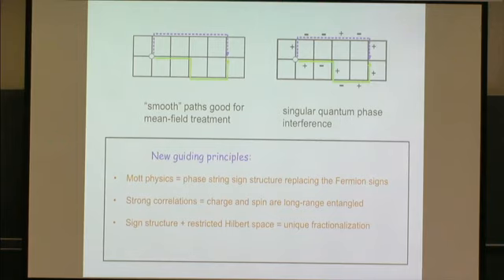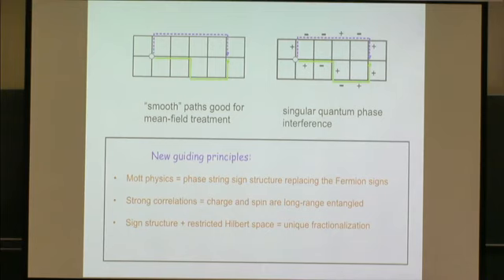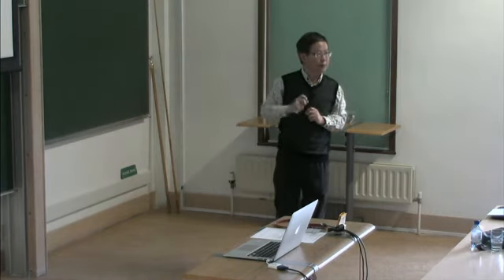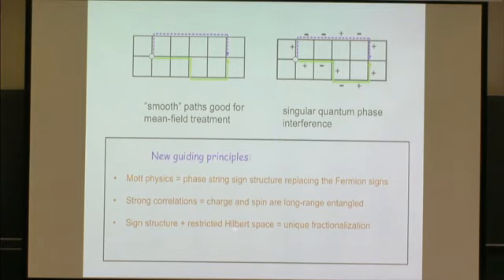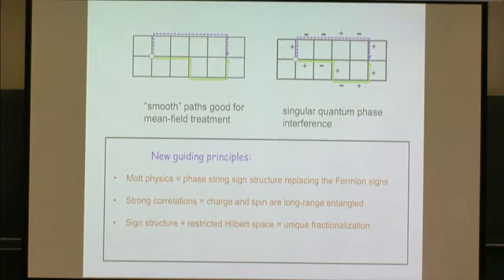And this could be regarded as the nature of Mott physics. So Mott physics shows that some kind of new sign structure replaces the fermion signs in the non-interacting limit. And this strong correlation represents that the charge here has a spin background with long-range entanglement. And this sign structure plus the restricted Hilbert space tells us we really need a unique fractionalization to deal with this system. In other words, you have to make some duality, we call it a mutual duality transformation, in order to treat this system. You cannot use the electron as the original basis to treat it. You would meet a tremendous singular perturbative problem. And so that's the moral we learn from this system.